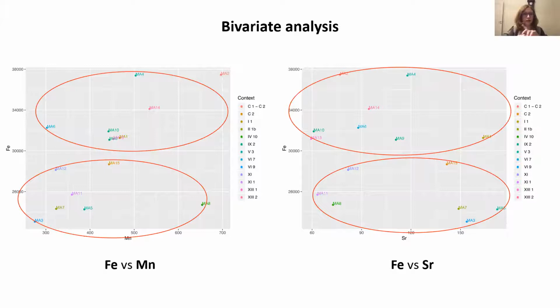Specifically, when we look at the graph on the left, where iron versus manganese is presented, we see an open arrangement of points that indicates that mudbricks that share a similarity macroscopically, what Maud was earlier presenting as heterogeneous or homogeneous, can show chemical dissimilarity. One example, for instance, is Ma2 and Ma15 from Corridor C. But more important, both scatter plots indicate a clear division in two main groups that show the chemical similarity between samples located in nearby walls, such as Ma9 and 10, 13 and 14, 7 and 8. Thus, referring back to the image of the chaîne opératoire that I showed you earlier on, this indicates that these mudbricks were produced within one single manufacturing phase, while their assignment to neighboring areas of the palace suggests a cluster construction development.